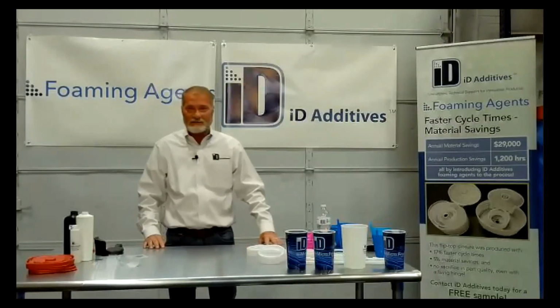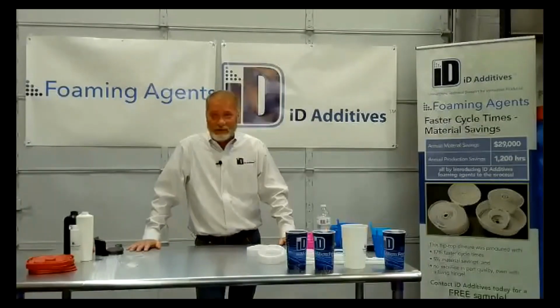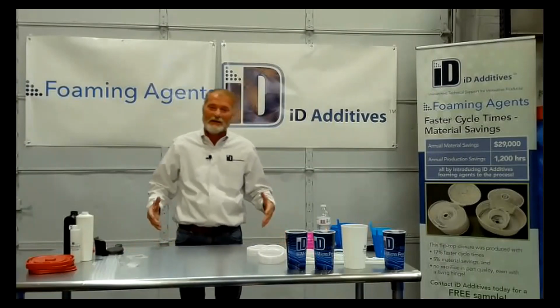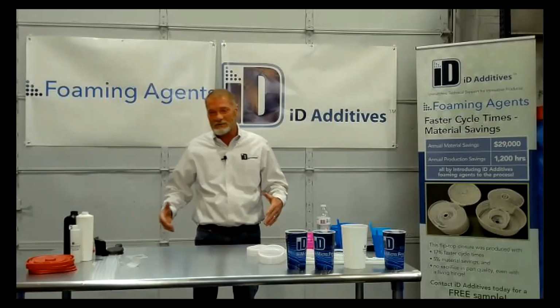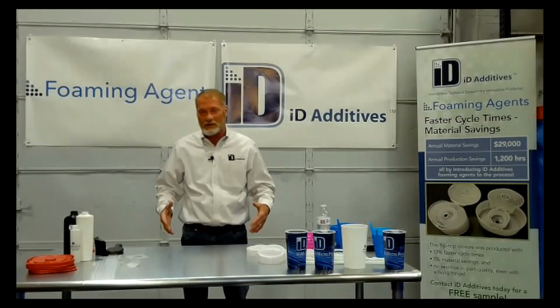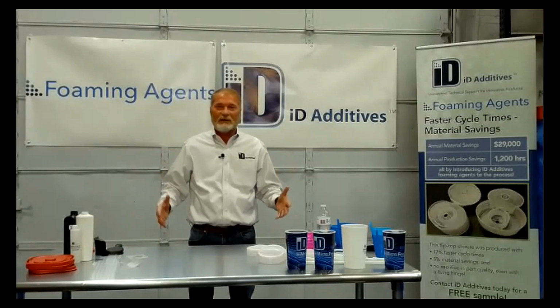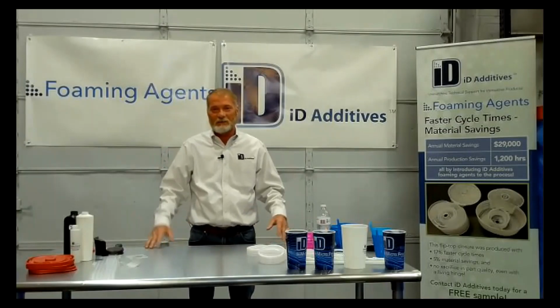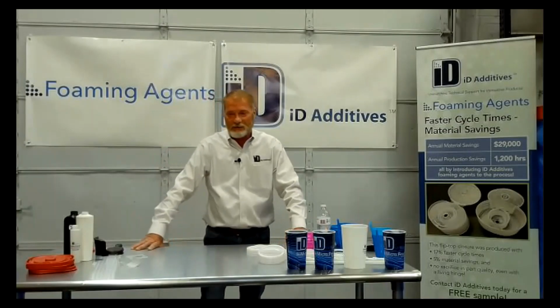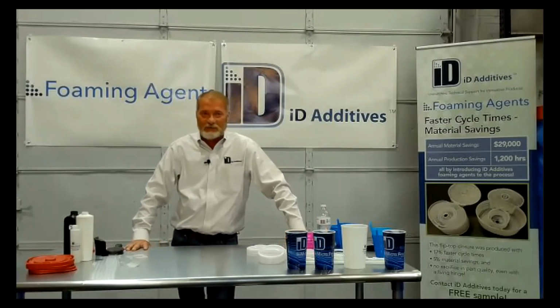Endothermics degas almost immediately. So within an hour, you can paint them. You don't have any problems with degassing. It degasses extremely fast. And that's why endothermics typically don't work that good in the extrusion profile, because they degas too quickly, they cool too quickly, and they don't hold profile as well as an exothermic. Big difference there, but with endothermics, you're pretty safe to do whatever you want to. Hot stamp, paint, do whatever you want to do with them.